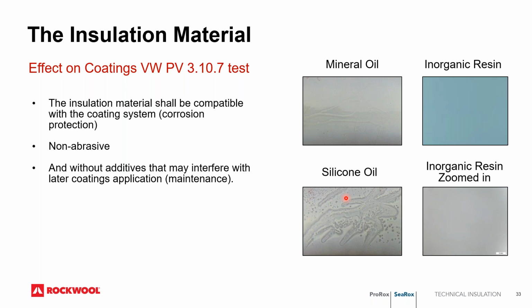On the right are the pictures of stone wool with different additive types being tested. The mineral oil caused poor paint adherence. With the silicone oil, you'll notice some fisheye effects as well as poor paint adherence. With inorganic resins, there are no visible defects even when zoomed in. If you happen to notice a difference of color in one slide, that's just based on the camera lighting as we zoomed in, just in case that was a question that may come up. So we are confident that inorganic resins are indeed safe for coatings.